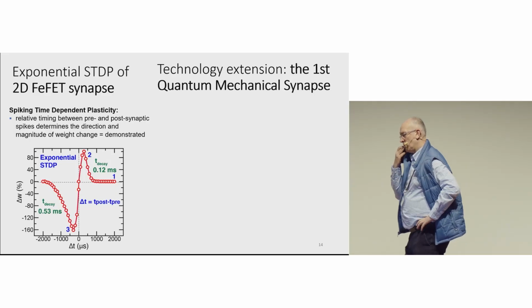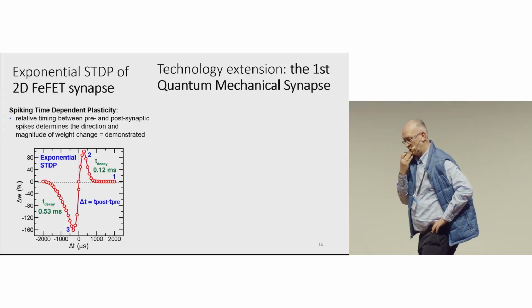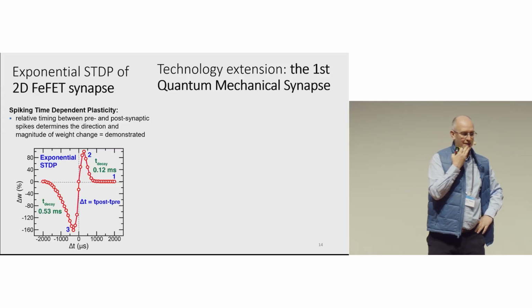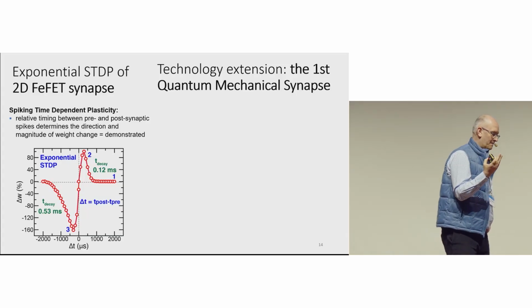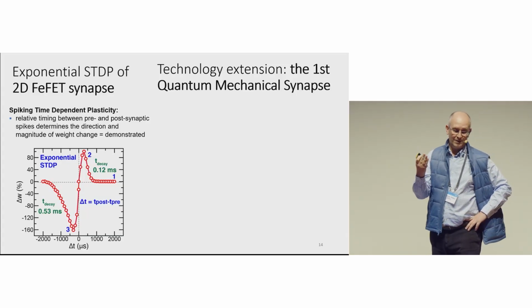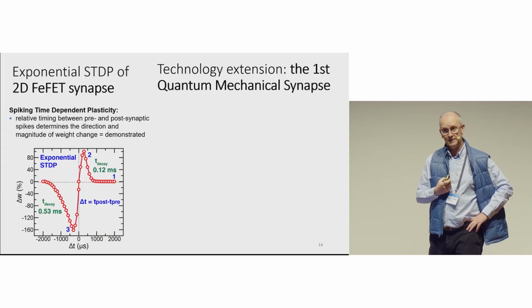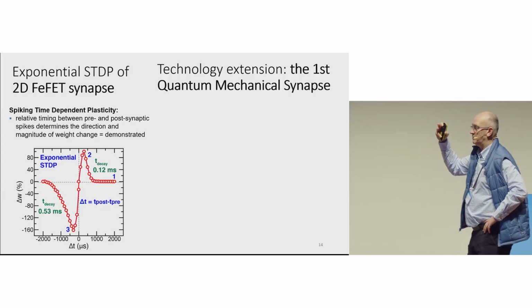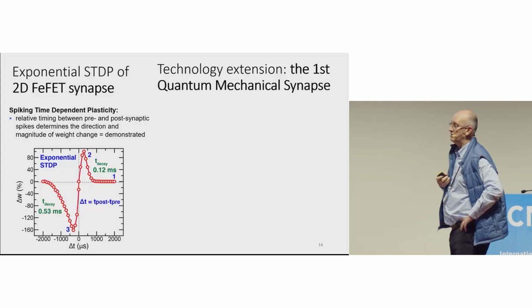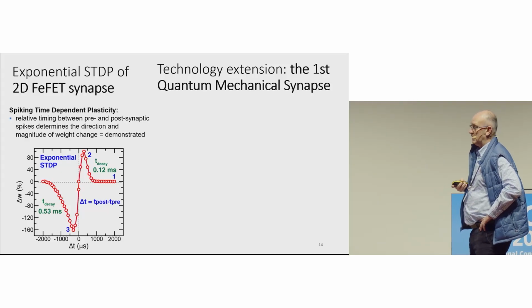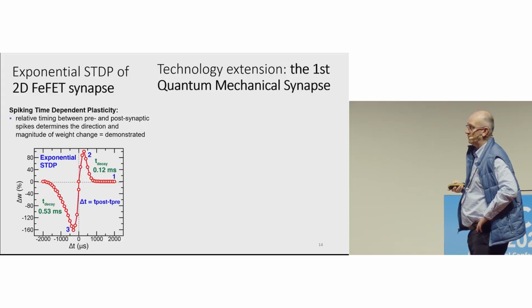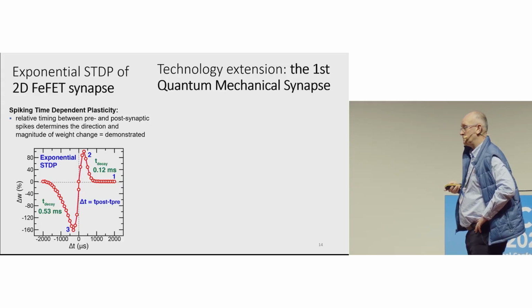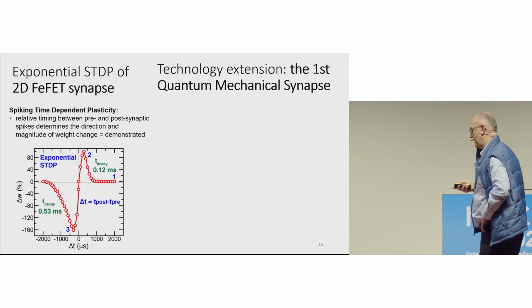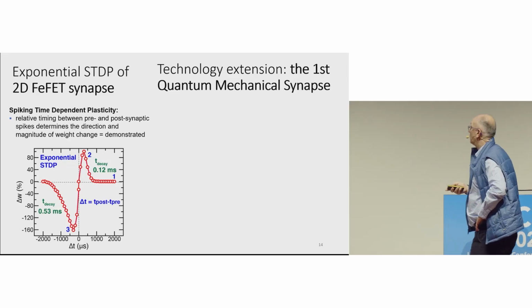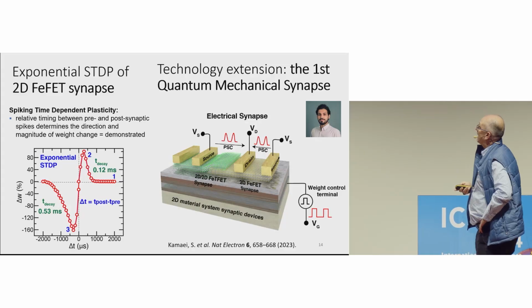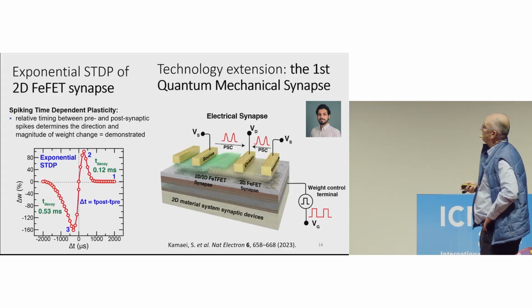Because in this domain, we have worked in the past a lot on steep slope transistors, which are based on quantum mechanical tunneling FET. And here I'm going to show you that we can make a quantum mechanical synapse that can have this hysteresis with a much more abrupt steep transition by using ferroelectric gating of tunneling FETs. And this is something I think very interesting if we want to make synapses in the domain of extremely low current and voltages. So here, what we have imagined is now a van der Waals tunnel FET.